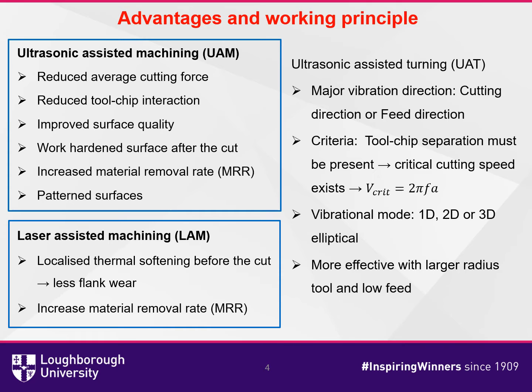For LAM, the main advantage is the localized thermal softening before the cut, where the softened area can be removed straight after by the tool. In general, if the heat is well absorbed, the radial forces are reduced, resulting less flank wear. Therefore, hybrid machining, combining the two, can be advantageous, but in this presentation the main focus would be on ultrasonic